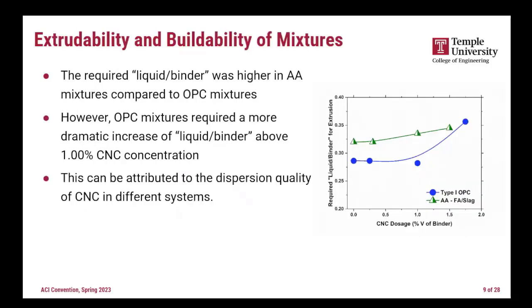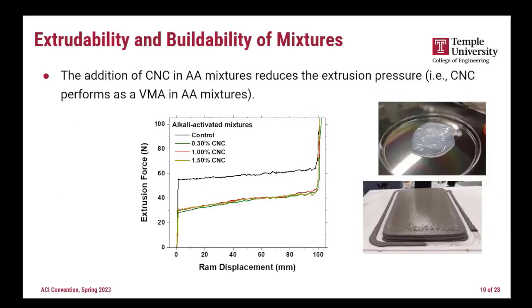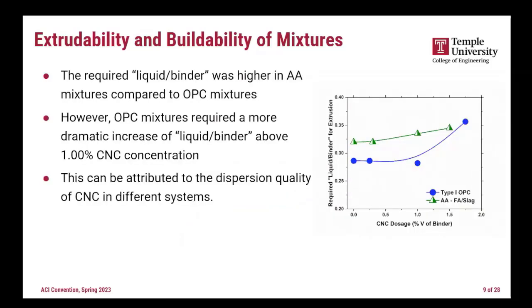Regarding the fresh properties, this is what I'm showing at the right side here. Here, the x-axis is the CNC dosage, the y-axis is the required liquid to binder ratio to be printable. So as you can see, for alkali activated system, we need more liquid to binder ratio to be printable, but for OPC lower. But something we noticed, after 1% CNC use, we see a higher exponential increase in the case of the OPC, and we think that's the critical point to reach agglomeration and aggregation of the CNC in the OPC system.